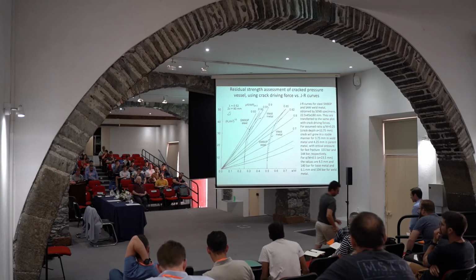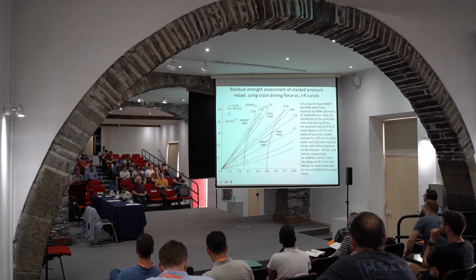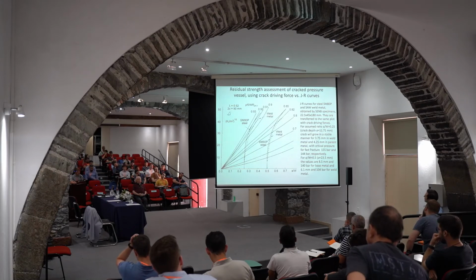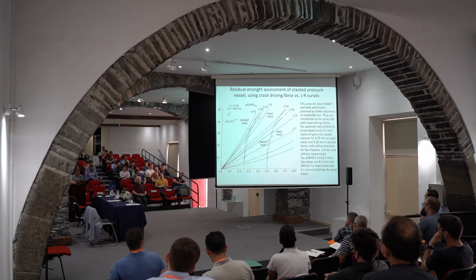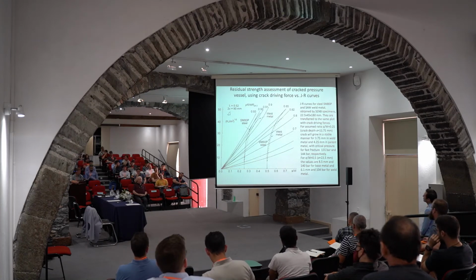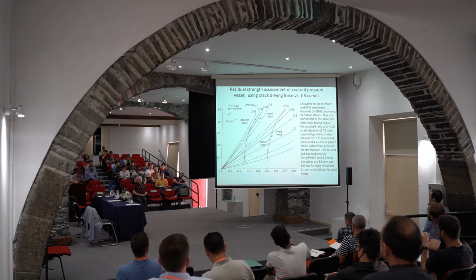Even with a conservative approach, even with the crack which is about half of the depth, we still need 85% of pressure to get to the critical state. And design pressure is about half that value. So in this way we proved numerically, analytically, experimentally, whatever, that the design was safe. But you can see that it is a very, very complex investigation. It was necessary because it was done for the first time under circumstances that I explained.